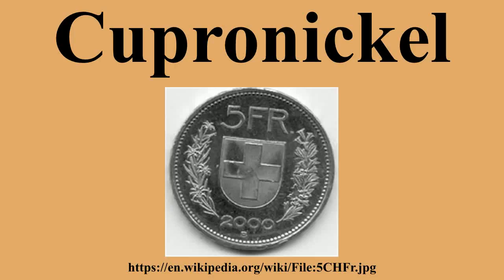To use this property to its full potential, the alloy needs to be free of the effects of, or insulated from, any form of cathodic protection. However, Cu-Ni alloys can show high corrosion rates in polluted or stagnant seawater when sulfides or ammonia are present. It is important, therefore, to avoid exposure to such conditions, particularly during commissioning and refit while the surface films are